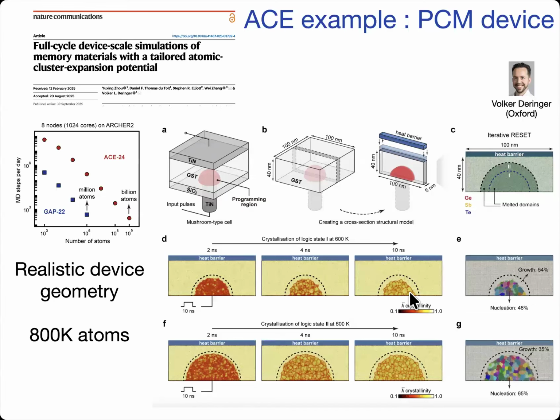And what they're doing here is applying 2 different heat pulses, and this is the amorphous state, the yellow. And then as you apply the heat pulse of a certain intensity and time duration, you get recrystallization. And what they're showing here is that depending on what kind of pulse they apply, you can control the amount of recrystallization. And you see the polycrystalline outcome at the end.